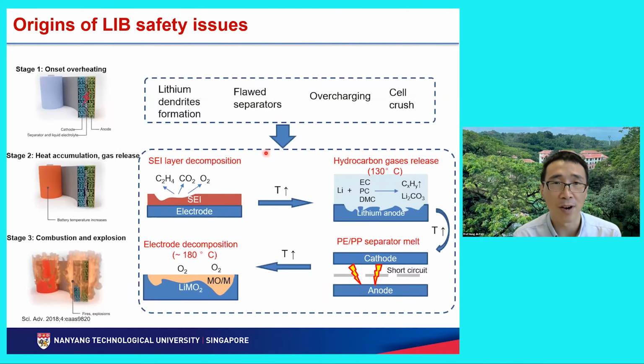Lithium batteries can catch fire for different reasons. It can be lithium dendrite formation that punches through between the cathode and anode side. It can be flawed separators. The separator is too thin, like with Samsung, right? The Samsung phones were all recalled because of the fire hazard, because they made the battery much thinner. The separator is so thin that the positive and negative sides may touch each other and catch fire. Overcharging is another cause: for example, if you charge these electric scooters overnight, it's overcharging. If they do not have a very smart temperature management system, then they can catch fire and also cell crush.